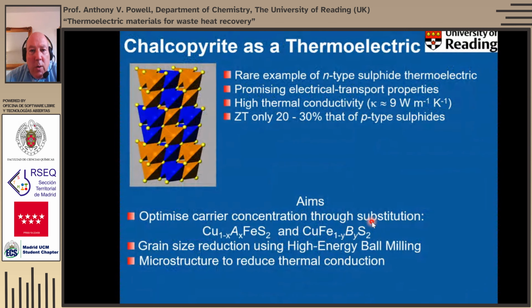Chalcopyrite is a really quite interesting thermoelectric material because it's a rare example of an N-type material, and it has quite promising electrical transport properties, but very high thermal conductivity. So its thermal conductivity is similar to an unfilled skutterudite, about 9 watts per meter per Kelvin. And consequently, its figure of merit is only about 20 to 30% that of the best P-type sulfides.